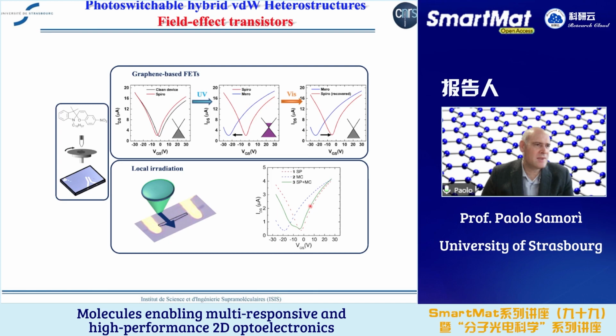And this you can see here, the new curve actually has a part that reflects the spiropyran content and another one that is left over of the merocyanine content. So this is the lateral heterojunction.